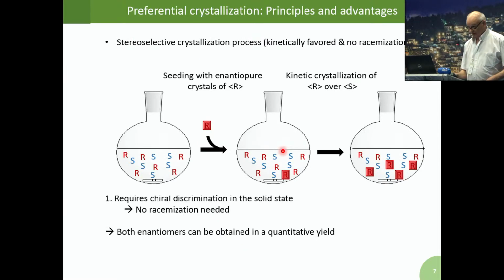Now, if your molecule cannot interconvert, so they are definitely right-handed molecule and left-handed molecule and then cannot interconvert, there is no RS equilibrium. If you have this chiral discrimination in the solid state, starting from a supersaturated solution by seeding with a single enantiomer, you can start crystallizing this enantiomer that you have seeded. Okay, and then you have secondary nucleation, and then you have a clear crystallization which is stereoselective, which is then preferential.